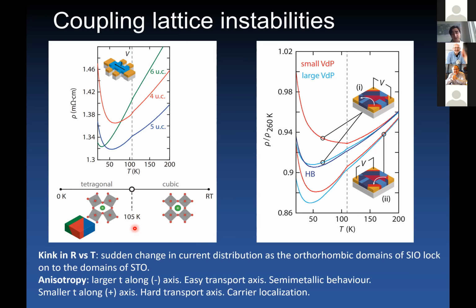And the anisotropy is explained by the fact that now we have this template in which along one direction, along the out of phase axis of rotation, we have a larger hopping parameter. So we have an easy transport axis along the direction, which is characterized by semi-metallic behavior. While along the in-phase axis of rotation, DFT tells us that we have a smaller hopping parameter. So that's a hard transport axis, and that favors carrier localization in the system. So we have a very interesting loss of symmetry in the system. So you go from a system that was symmetric with respect to in-plane rotations to now having a highly anisotropic character.